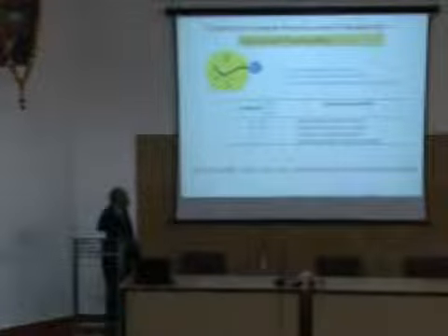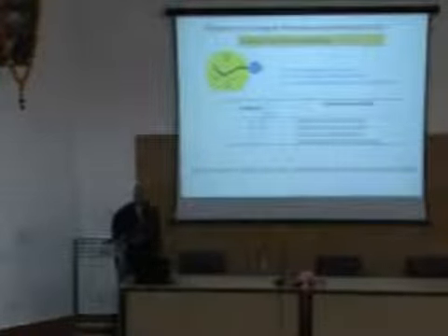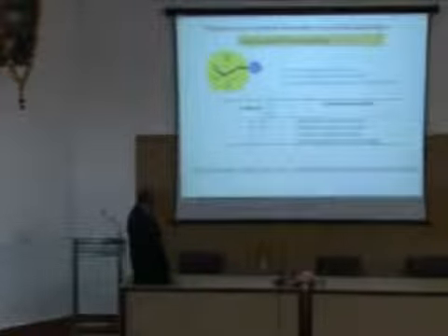So there are certain parameters, when you choose a surfactant, you have to know the area of the head group and the volume of this micelle, which will depend on the length of the hydrophobic tail, and depend on this factor, which is called the surfactant packing parameter. You can generalize that you will get a shape of this kind. So you have to choose these numbers which will give you the type of aggregate that you need in which you want to do your material synthesis. Okay? So there are some more details, if you want, I can discuss later.